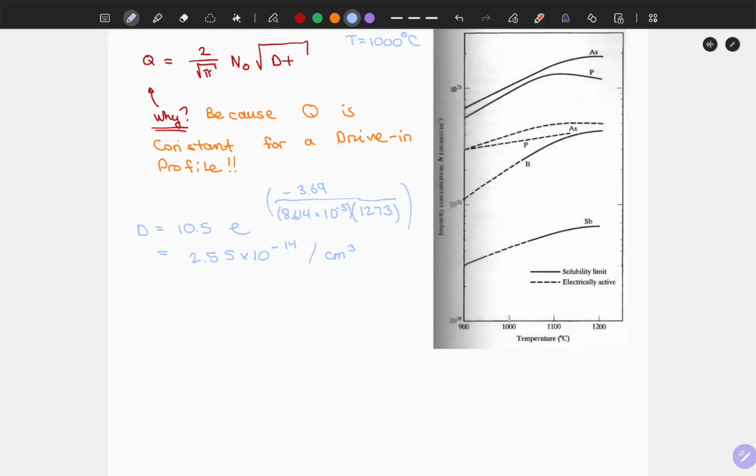And if we then take this temperature and follow the solubility chart for boron, we get approximately 2 times 10 to the 20th. So this chart relates the concentration to temperature, where this is a solid solubility limit, meaning the concentration is actually limited. And like adding salt to water, as we increase the temperature, we can see how the solubility limit generally increases.